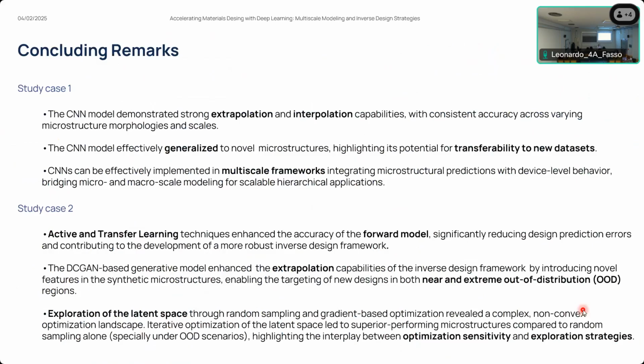Regarding the second study case, where instead of just using the predictive part, we also incorporate the generative part to obtain this inverse design framework, we can conclude that active and transfer learning was very effective to improve the accuracy of the forward model. Importantly, the GAN-based samples significantly enhance the extrapolation capabilities of the inverse design framework by introducing new features in the synthetic data, so in the synthetic microstructures. This enables us to target new designs in both near out-of-distribution and extreme out-of-distribution regions of the material property space.